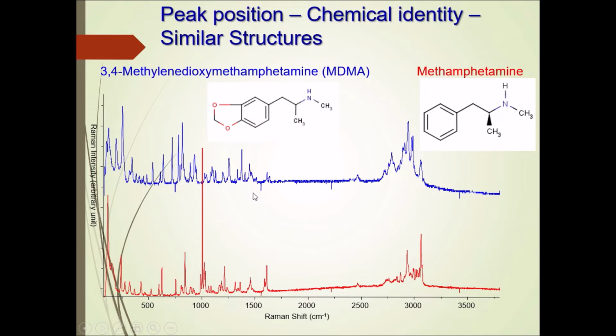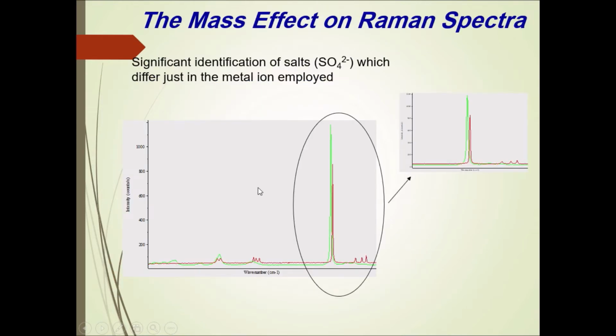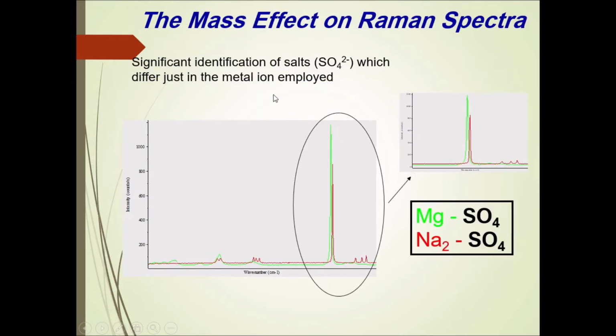Also for the chemical identity of similar compounds, like this blue and red spectrum of methamphetamine and MDMA, we can see that both compounds have more or less the same structure, except that here we have two extra oxygen atoms. For this red compound we can see sharp peaks, which are different from the blue one, so we can distinguish between these two similar compounds. Also, using Raman spectroscopy, we can distinguish between different salts like magnesium sulfate and sodium sulfate.